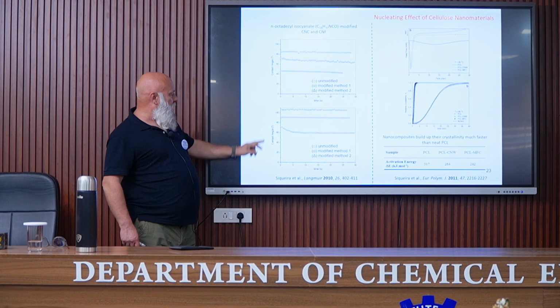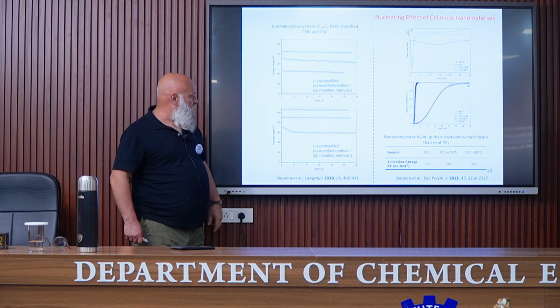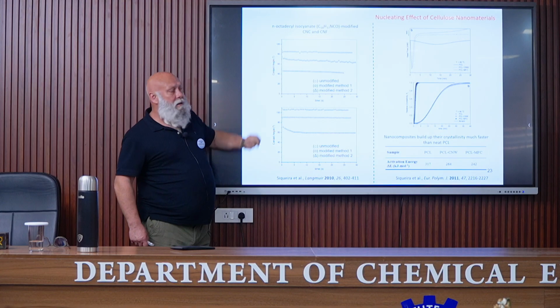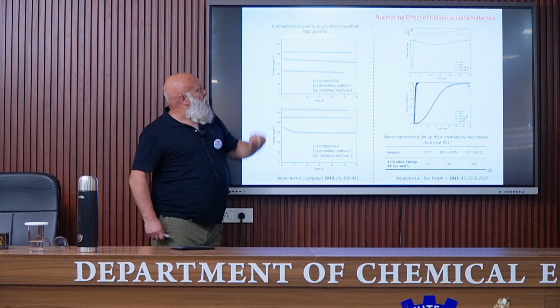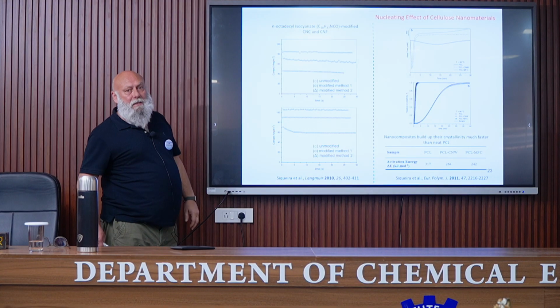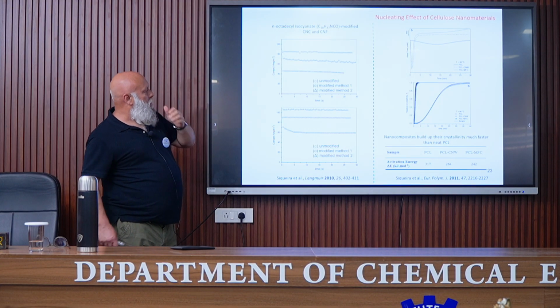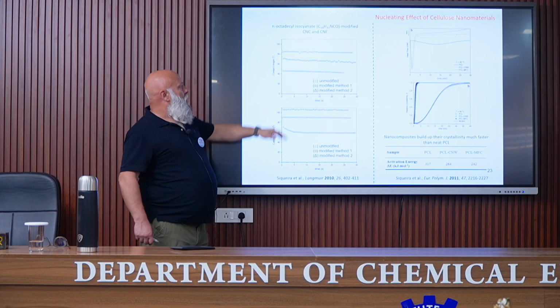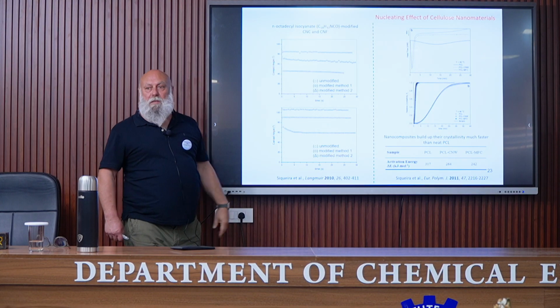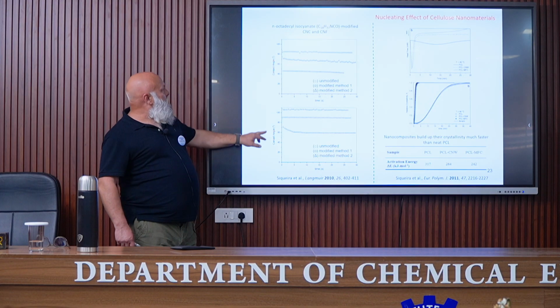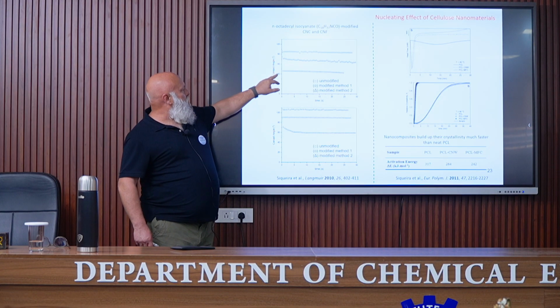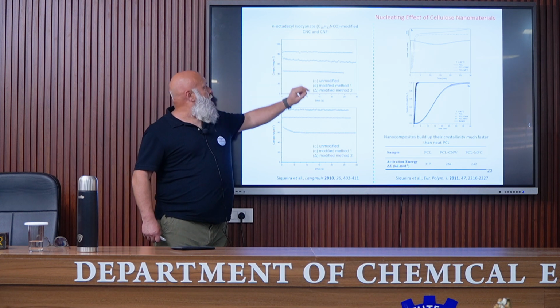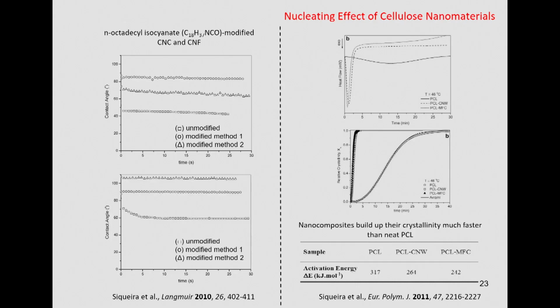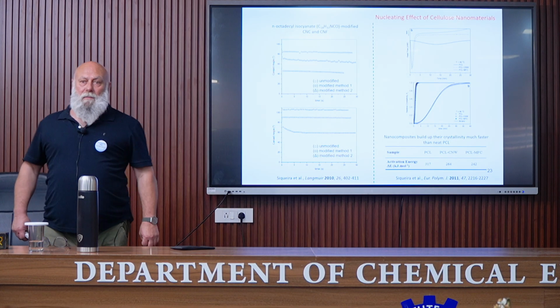I will show you an example. This is for cellulose nanocrystals, this is for cellulose nanofibrils, contact angle as a function of time. This is for unmodified nanoparticles, and here, nanoparticles that have been modified with an isocyanate, following two different strategies, two different methods. Of course, after modification, the material is more hydrophobic. What is interesting to see also is that for cellulose nanocrystals, the contact angle is around 40, maybe 45 degrees. For cellulose nanofibrils, it is around 60 degrees.